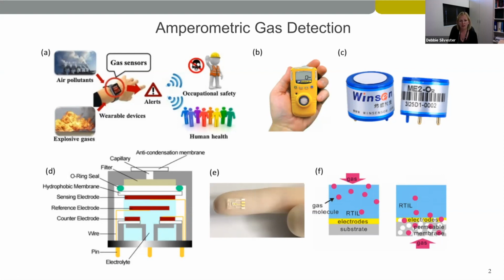And so the main difference is the way that we use these is we drop a small volume of a non-volatile ionic liquid onto the top. And so we have the situation in figure F, where the gas goes in, partitions in from the gas phase into the ionic liquid. Once you have an equilibration, then the gas diffuses to the electrode where it's oxidized or reduced. And this is different to the commercial sensors in that normally the gas goes through the permeable membrane and reaches the electrode before going into the solvent.